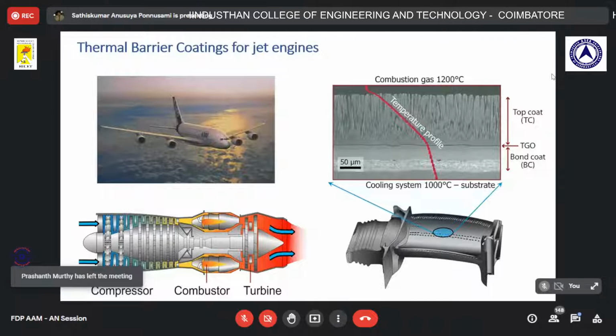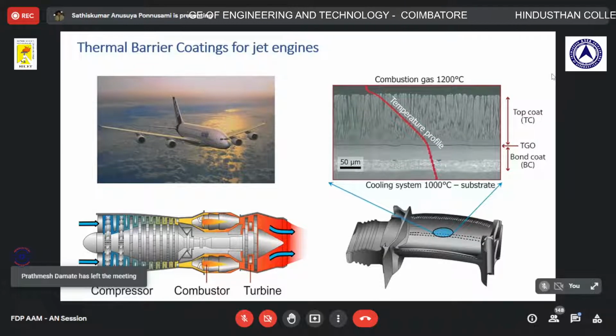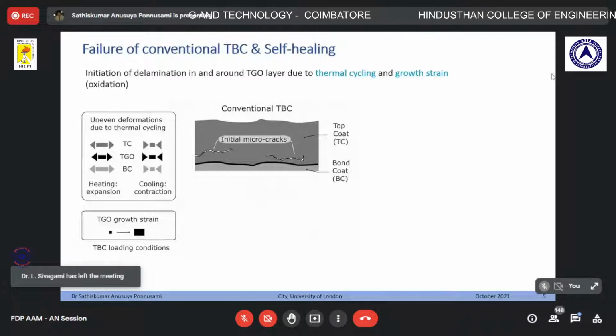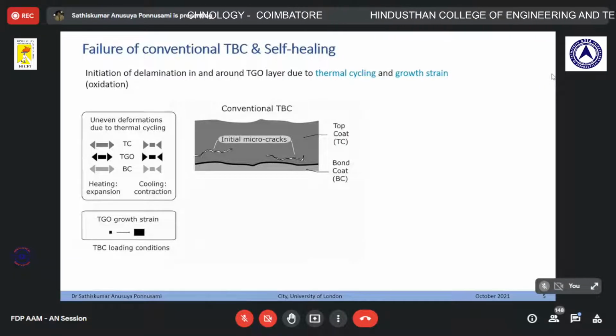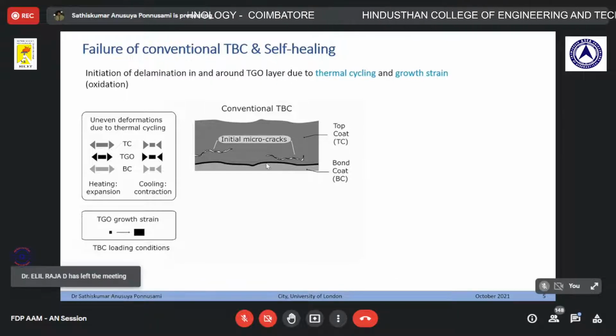And those thermal stresses during operation, meaning every takeoff and landing, those stresses create cracks, micro cracks. And that is what you would see in the next slide. Yeah. So that is a schematic of the thermal barrier coating. We call it as TBC. Yeah. And you see little micro cracks there. And that is created due to the thermal stresses. And during operation, you see a little black line in the middle, if you can. So that little black line is basically called an oxide layer, which grows continuously during the engine operation, meaning every takeoff and landing, the thickness of that particular black layer, the oxide layer, keeps growing.